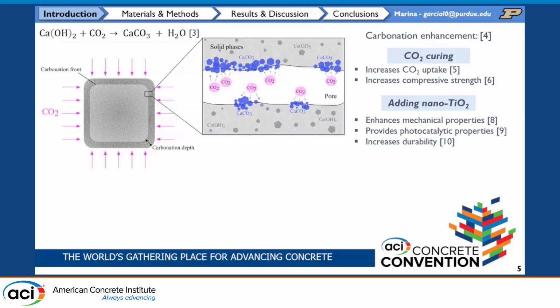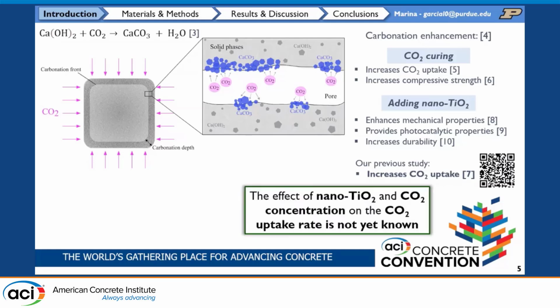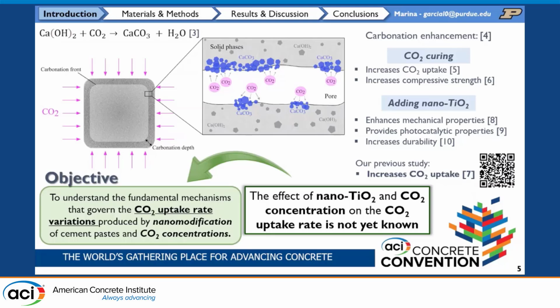Also, the addition of titanium dioxide nanoparticles has been found to enhance these mechanical properties, provide photocatalytic properties as well, and increase durability. And in one of our recent studies, we actually found out that it also increases CO2 uptake of our cementitious composites. However, the effect of titanium dioxide nanoparticles and the CO2 concentration in the air on how fast this reaction is, is not known. Therefore, the objective of this particular study is to understand the mechanisms that govern these changes in the CO2 uptake rate, or the acceleration of this phenomenon produced by the nanomodification of cement pastes and those CO2 concentrations.